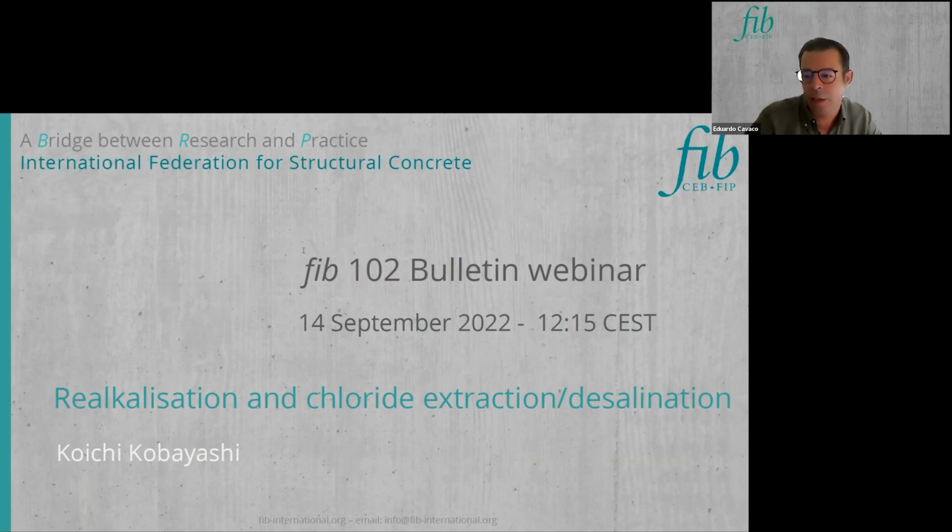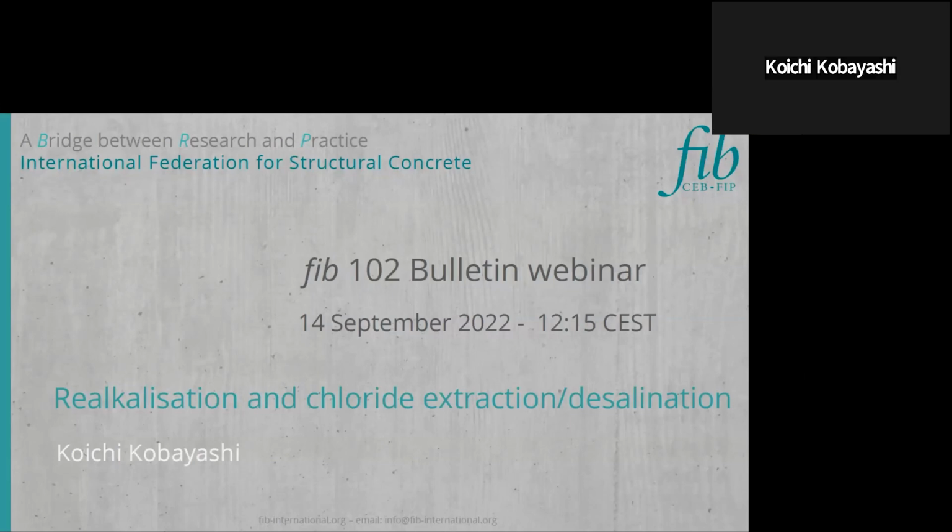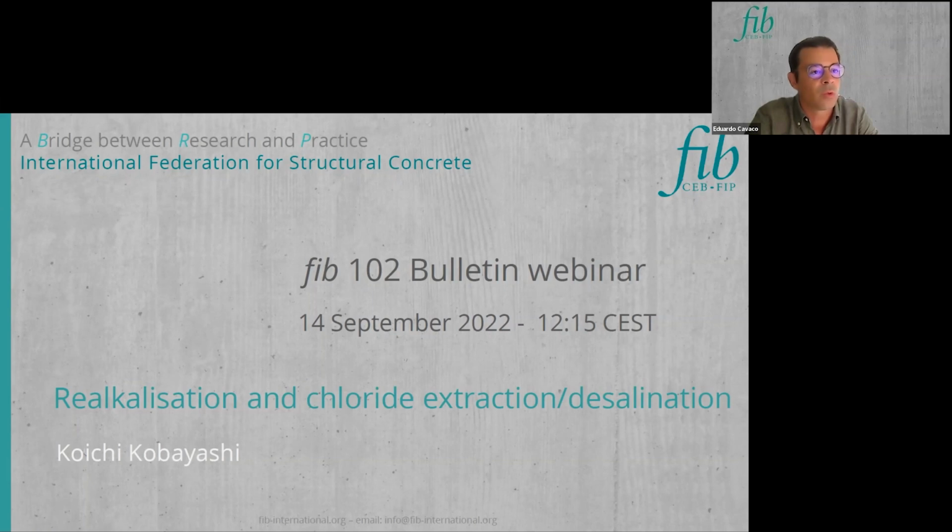Maybe I have just, I think it's more a curiosity. I saw, when comparing these methods with the cathodic protection, the currents you have to apply are much higher. You said up to 5 amps per square meter and voltage up to 50 volts.